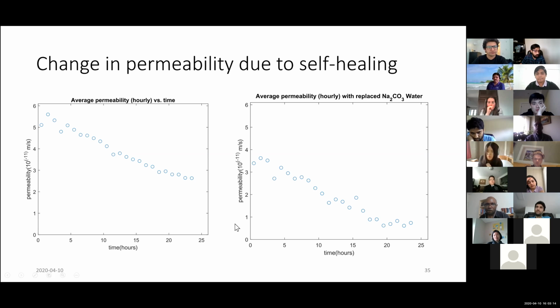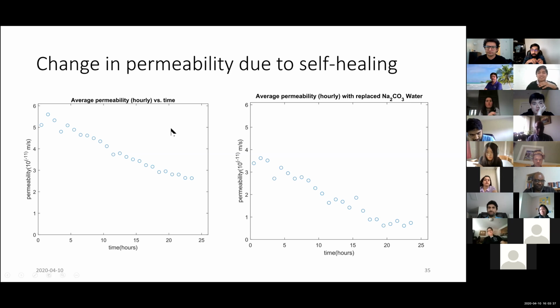I have tried this test on the 7th and 14th day as well. But in terms of comparative values, once I redo the test, I take out the samples and put them back in, there is a lot of initial difference after reloading the sample. So most of the tests that I did, I can't really compare these two values because this turned out in some different domain from this, because the difference is almost 70-80% between the two.